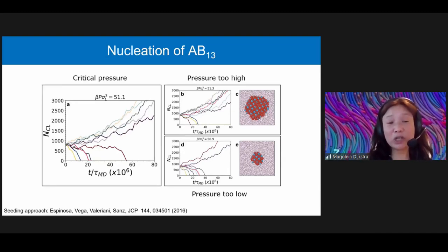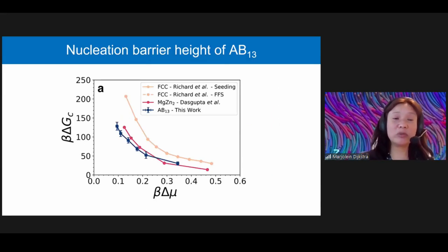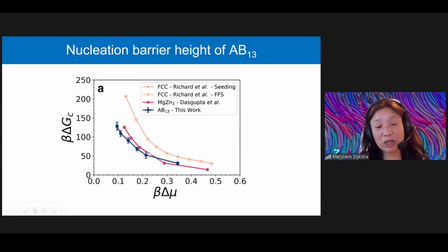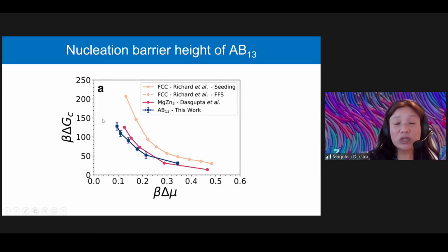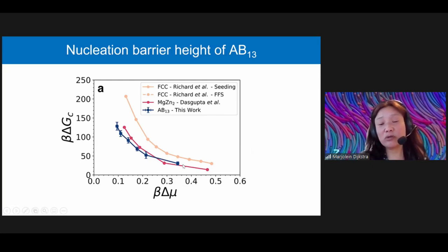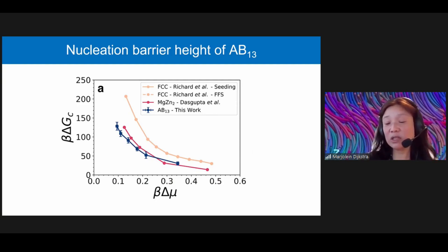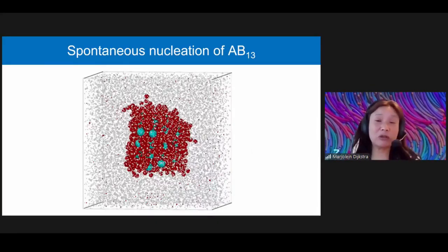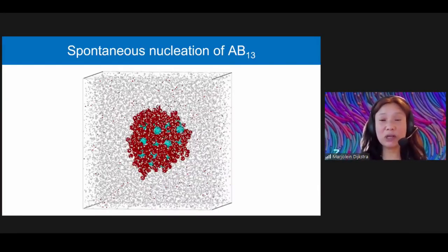And by calculating this critical pressure, we can also calculate the supersaturation, and using then classical nucleation theory, you can determine the nucleation barrier heights. And that's denoted here by these blue symbols, and we compare it with just the hard sphere nucleation with also another binary crystal phase. So using this data, we can also extrapolate the barrier height towards higher and higher supersaturation, and we can pinpoint where the nucleation barrier is sufficiently low that we should be able to find spontaneous nucleation. So when the barrier height is less than 10 kBT, we can expect to find spontaneous nucleation.